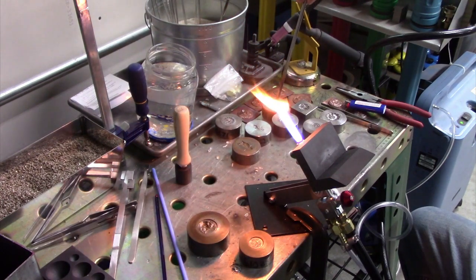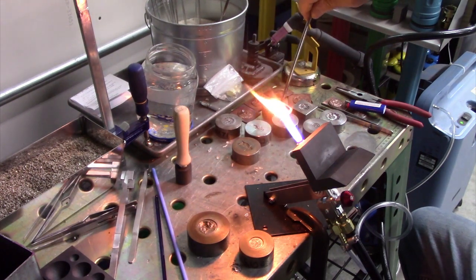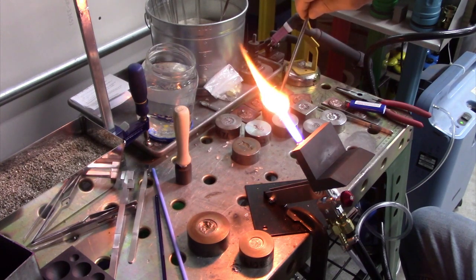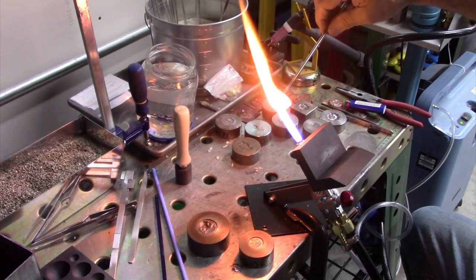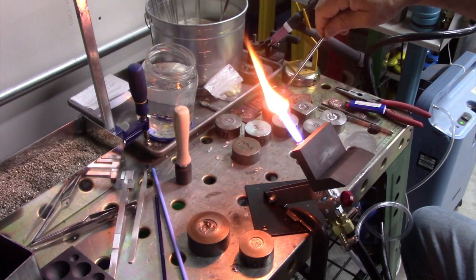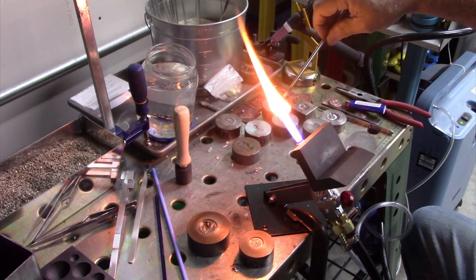Now what I want to do is leave this in the flame long enough that it is sort of uniformly molten. If you rush that, I guarantee you will not get a good pressing, and it'll have so much stress in it because of the different temperatures, and you're going to be rapidly cooling this anyway. We're always working on the edge of what you can do without thermally shocking the hell out of everything. Anyway, so we'll just let this become a molten puddle, carefully holding it over this steel table, not your lap, because as you can see, it's moving around.